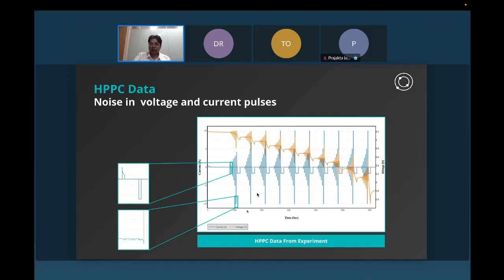Now, here is a typical example of an HPPC experiment. Usually what is done is you start with a fully charged cell, and then you start giving the charge and discharge pulses. And during these pulses, you monitor the voltage. There are certain signatures in the voltage during these pulses which are very important to understand the characteristics of these cells. I'll come to that a bit later, but I wanted to highlight at this stage that there are various types of problems that you will see in the experimental data. First thing that you would notice is sometimes these pulses are not very flat, and because of something happening in these experiments, you would see that the pulses have this kind of shape.